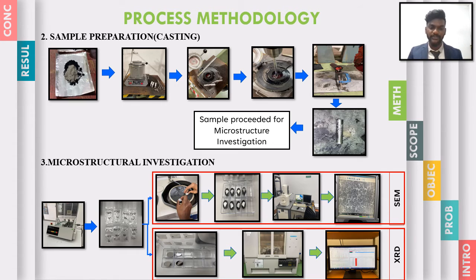For the microstructure investigation, there are two different techniques, which are SEM and also XRD. For the SEM, we cut the samples into small pieces using a diamond cutter, and after that the samples are polished and then mounted using resin, and after the mounting it was polished again, then given to the SEM laboratories for the microstructure characterization.